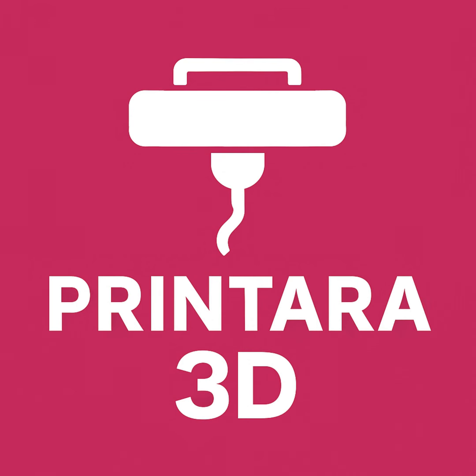Unfortunate, but true. A Bowden setup is physically incapable of reliably feeding highly elastic material. Think about how a Bowden system is constructed. Right. The heavy extruder motor and the driving gears are mounted all the way back on the frame of the printer to keep the print head light. Yeah, so those gears have to bite into the filament and push it through a long PTFE tube, which is essentially a plastic straw, all the way to the moving hot end. Exactly. So you have got this massive 40-centimeter distance between where the pushing happens and where the melting actually happens.